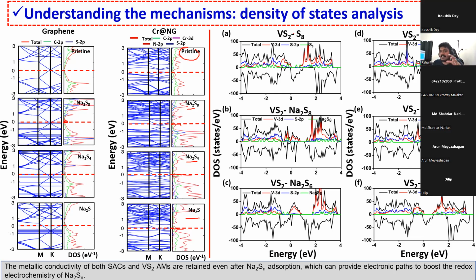And again, we have the VS2 material. You can see that VS2, as I previously told, is conductive in nature. You can see clearly that the total is nothing but the density of states of the pristine VS2. You can see that the VS2 itself is conductive in nature, and even after polysulfide adsorption, you can see that at the Fermi level, the conductivity is retained.